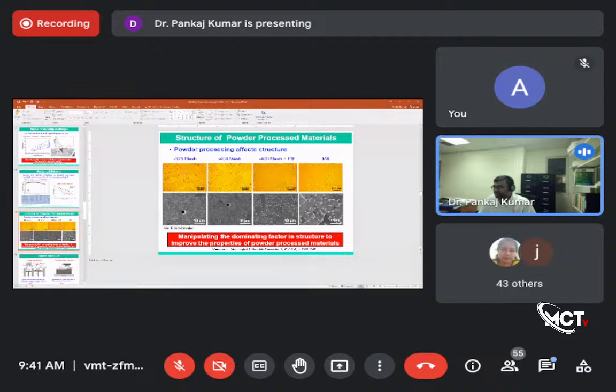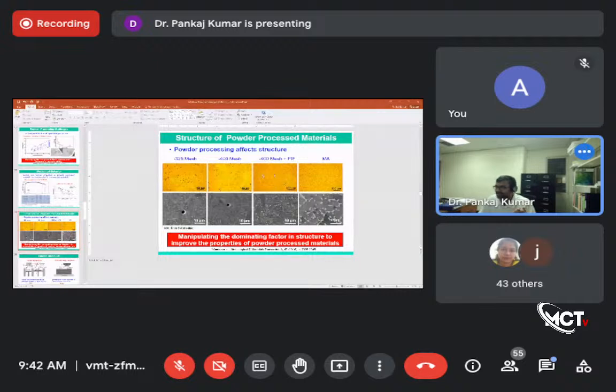If you look at the microstructure of those powders, starting from -325 mesh, which is the coarser particles, and this is finer particles, right? You see the significant difference in the defects. The black dots you see are pores. As soon as you apply the post-processing isostatic forging technique, all these defects have been completely eliminated, and the microstructure looks like your wrought product. So by manipulating the dominating factor, you can improve the properties of your material.